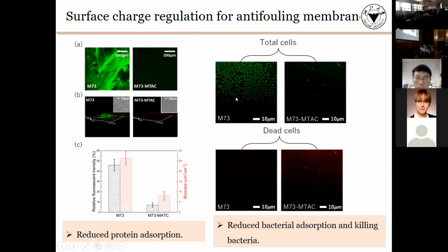For the original membrane, there are many bacteria on the membrane, but almost no dead bacteria on the surface. But for our modified membrane, there are few bacteria attached on the surface, and all the bacteria have been killed. That means our membrane has a very good antifouling and antibacterial property.